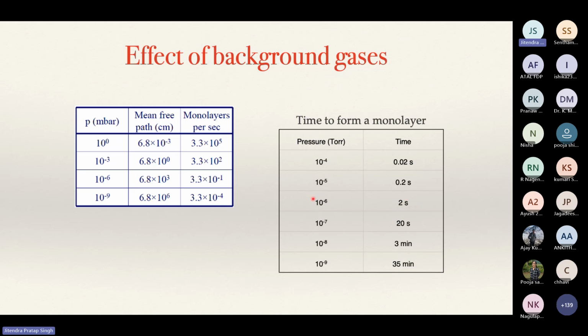But if I keep my vacuum at a very low pressure, if I go to ultra high vacuum, which is 10 to the power -9 torr, then you see one monolayer formation takes 35 minutes. So if I can quickly get the deposition under ultra high vacuum, then I can make sure that my film is contaminant free. These numbers are very useful when you really want to deposit contaminant free thin films.